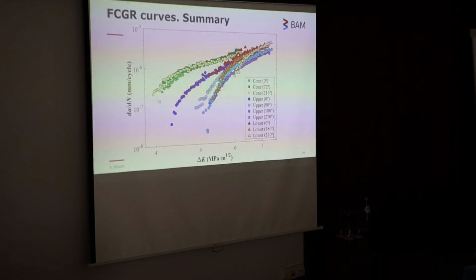Last question. As I understood, you associated this worst region of fatigue crack growth with residual stress. Yeah, I think so. In fact, as you can see here, the scatter in the upper and lower part is huge compared with the usual response of conventional materials, but in the case of the cone, the scatter is much lower. So we assume that due to the higher effective load ratio condition, this is the reason the scatter is much lower. Basically, we think that here we are working under crack closure free effects.